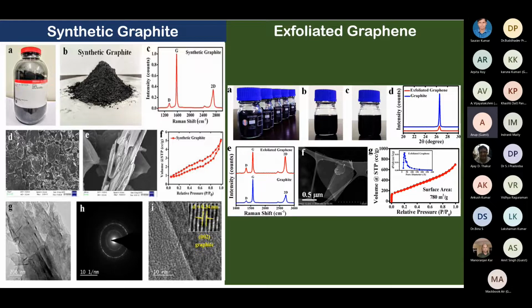After this, image number E is a Raman spectroscopy image of the graphite and the exfoliated graphene. Graphite was showing D and G peaks, which are the characteristics of graphite or carbonaceous material, at 1350 and 1580. And then around 2700 per centimeter, that is the 2D peak. We can see that the exfoliated graphene also shows a similar signature, and to our surprise, the 2D peak has a much higher intensity in the exfoliated graphene, which is the representation of very high purity graphene.